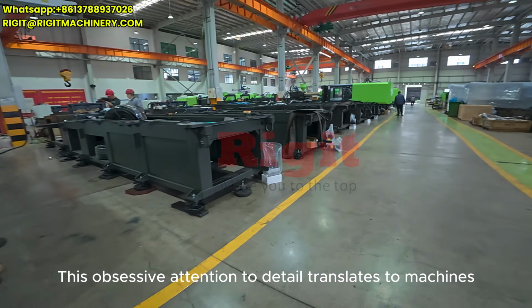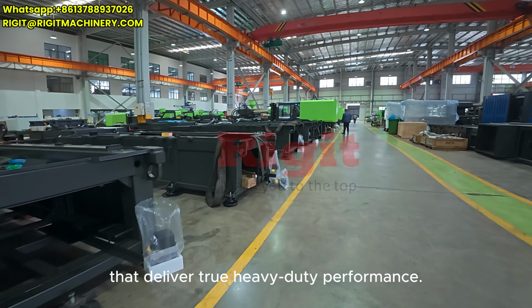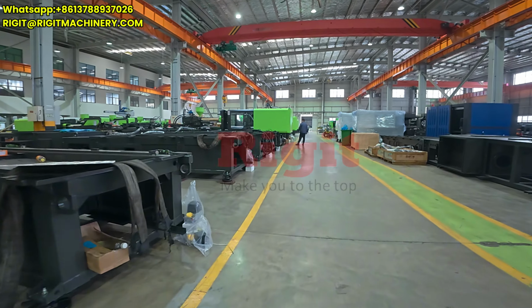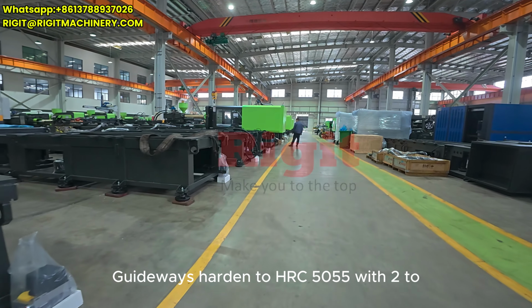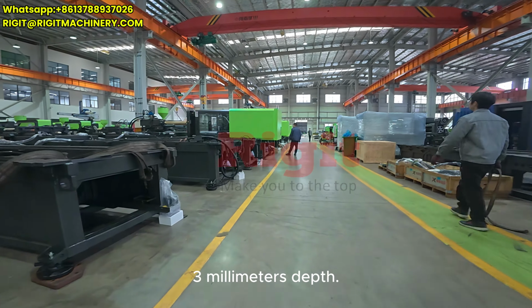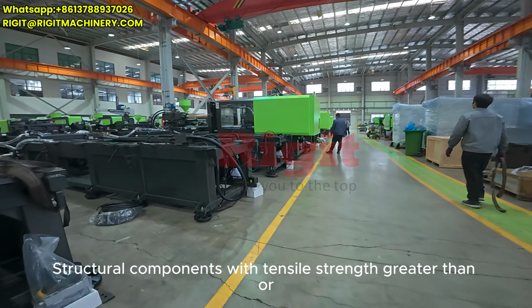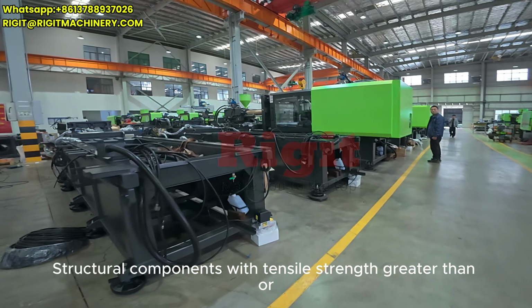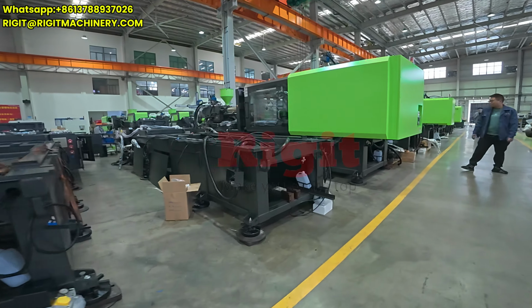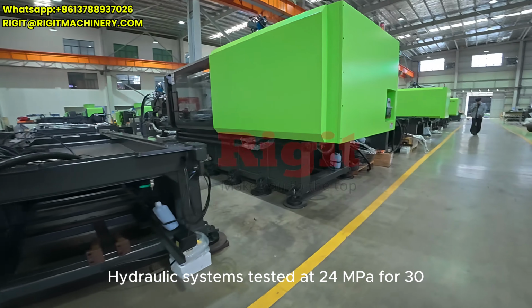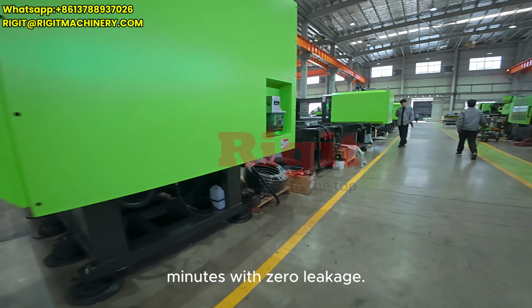The heavy-duty difference. This obsessive attention to detail translates to machines that deliver true heavy-duty performance. Guideways hardened to HRC 50-55 with 2 to 3 mm depth. Structural components with tensile strength greater than or equal to 800 MPa. Hydraulic systems tested at 24 megapascals for 30 minutes with zero leakage.